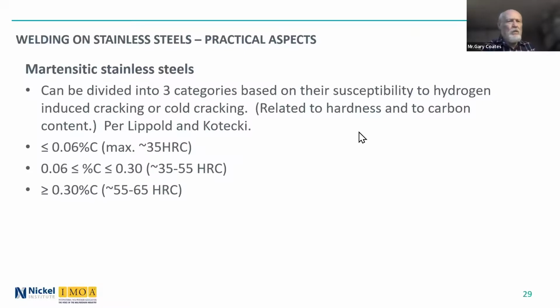I'm going to just briefly talk about martensitic alloys. You can divide them into three categories. A lot of the lower carbon versions are used in the oil and gas industry. And so the ones that have less than 0.06 carbon, typically maximum hardness is 35 Rockwell C. There's an intermediate carbon level that gives higher hardness, 35 to 55. And then there are the grades that you really want hard, 55 to 65 Rockwell C, and typically they have more than 0.30% carbon, so very high carbon content.